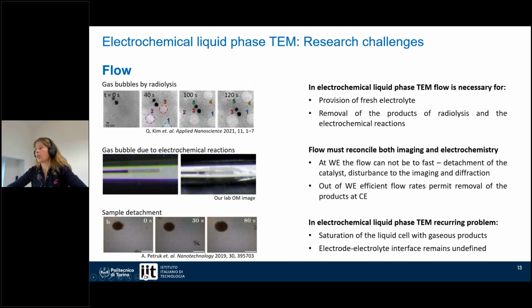So as you have seen, in electrochemical liquid phase TEM, flow is necessary, for the provision of fresh electrolyte and for the removal of the products of radiolysis and electrochemical reactions. And actually, efficient flow could remove the products before they create bubbles that dry the electrodes. And this could happen both in the case of radiolysis and in the case of products created by electrochemical reactions.